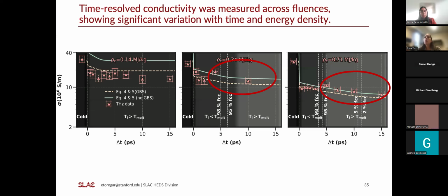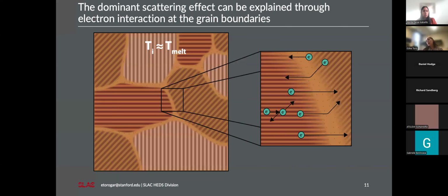However, going forward, why does the system suddenly behave as if the grain boundary scattering, the structural effects, never mattered? The reasoning is simple. When we are looking into grain melting, the grains start melting from the outside to the inside. And this hard, rigid boundary that you used to encounter in the past now becomes a soft transition between the different lattices.